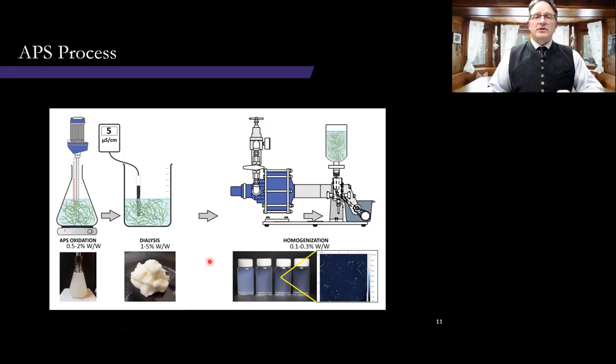And in our process, we use high pressure microfluidization and or ultrasonication, followed by centrifuging the samples. The resulting samples look like this lower left or lower right picture here. This sample here is high charge, this sample is low charge. So at a constant concentration, as the charge is increased, our colloidal stability improves and the transparency of our product increases.